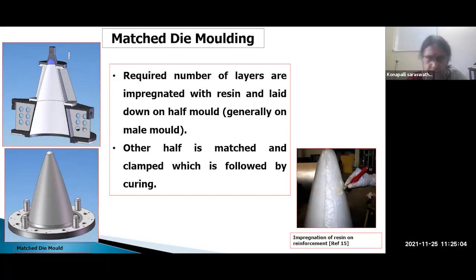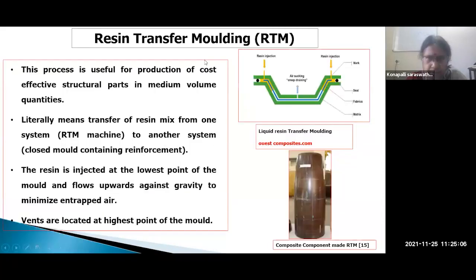Then transfer molding. This process is useful for production of cost-effective structural parts where both-side finish is required and medium volume, not very high volume. So there we use RTM. RTM literally means resin transfer from one machine to the preform. In one mold, we make the preforms and stack them, and resin is transferred from another system from the bottom through the nozzle under pressure. And from the top, if we require less time to get impregnated, we can apply vacuum and pull the resin against gravity. So this is how RTM is used.